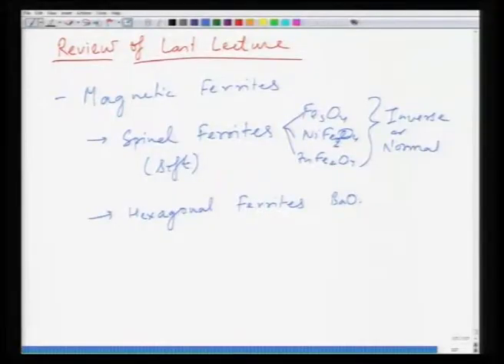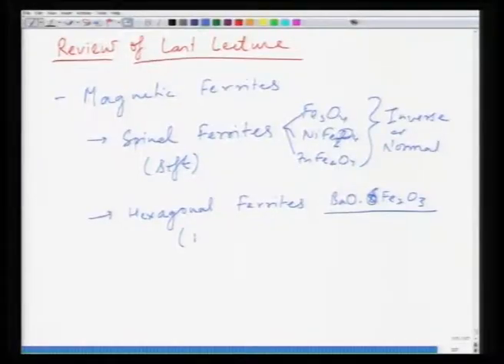This is a hexagonal unit cell. You can express this material as BaO·xFe₂O₃, and essentially x happens to be 6. This happens to have a mixing of FCC-based and HCP-based layers. Since FCC and HCP packing are fairly similar — except that in FCC you have ABC ABC and in HCP you have AB AB packing — they mix with each other quite well, resulting in a structure which is hexagonal in nature. This material also has large magnetization based on the distribution of iron atoms, since iron is the magnetic species here. This material is highly anisotropic and as a result it is called a hard magnet.